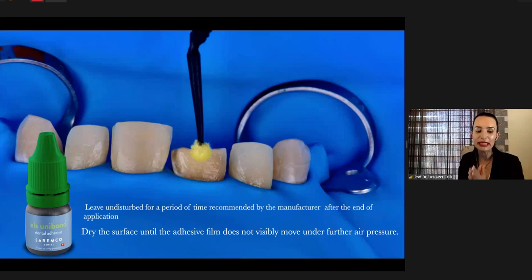Apply the adhesive system, and leave it undisturbed for the period of time recommended by the manufacturer after the end of application. This is generally 10 to 20 seconds for each adhesive system. And then dry the surface. This is very important to remove the solvents in the adhesive system. You have to remove ethanol or other solvents until the adhesive film does not visibly move under air pressure. This is very, very important, because if you do not remove it well, then probably it won't polymerize well. And this will cause many problems in the long-term clinical performance of your restoration.